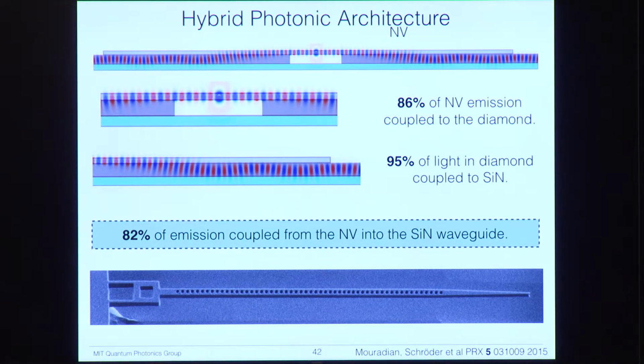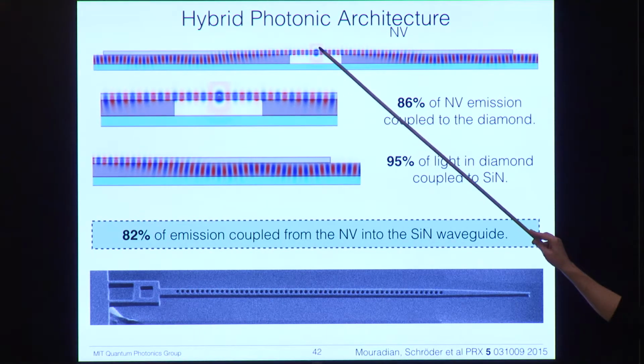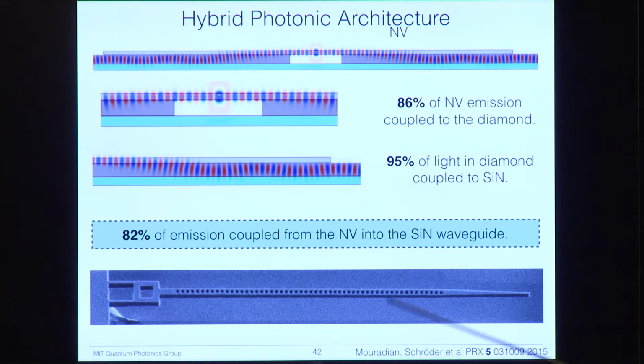Unlike a monolithic photonic integrated circuit, you also have to then convert the mode of the diamond photonic structure into the mode of the silicon nitride backbone. And so we do that with these tapers. These tapers adiabatically convert the mode in the diamond waveguide that is confined here into the silicon nitride waveguide here. So we can get a full 82% of emission coupled from the NV into the silicon nitride waveguide. So that's 86% of the NV into the diamond waveguide, and then 95% from the diamond to the silicon nitride. And this was all done without cavities, so just pure waveguides. But of course, this emission could even be enhanced by a cavity, and the rate could increase.